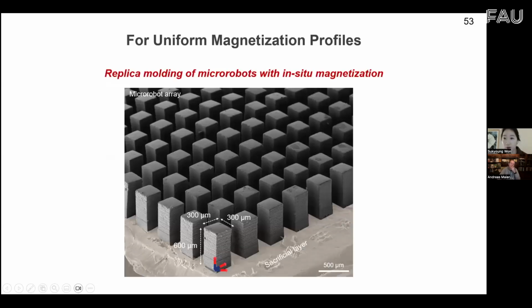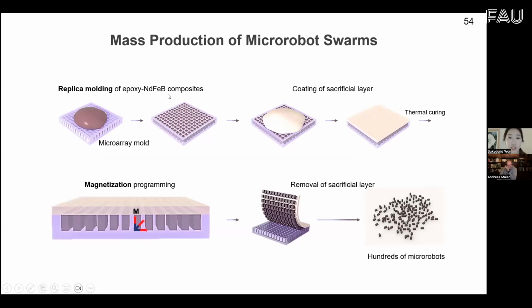However, how can we obtain these microrobots with mass production? So we prepare the microrobots by replica molding, using a microarray with a composite of 100 microrobot structures in a single master array, and we apply in situ magnetization to encode the magnetization profiles. After the hard magnetic particles are dispersed in the epoxy precursors, we replicate this structure, apply thermal curing for the robot preparation, and also apply the magnetization profiles at a higher coercivity magnetic field. Then we can obtain 100 microrobots simultaneously using a single microarray mold.